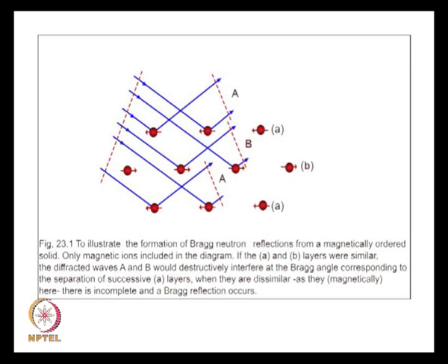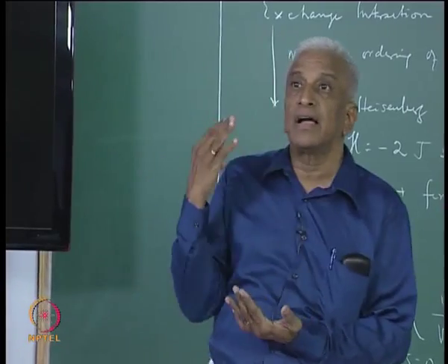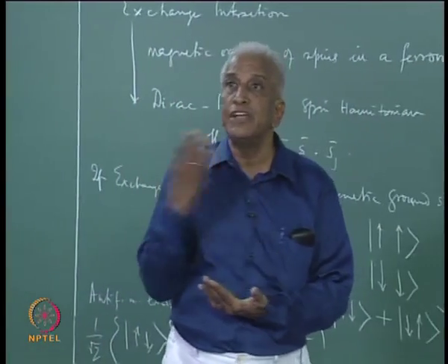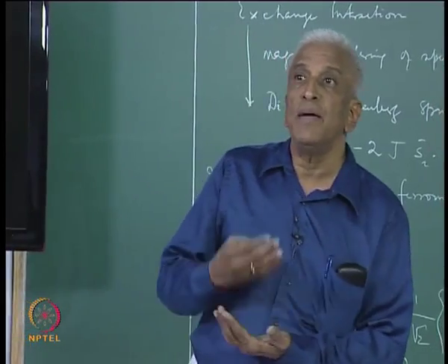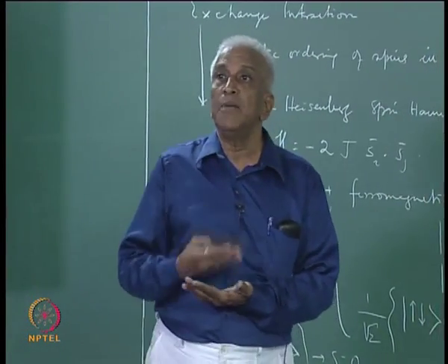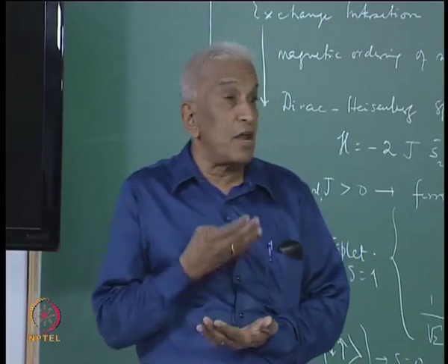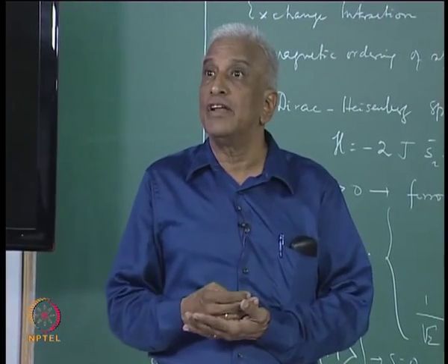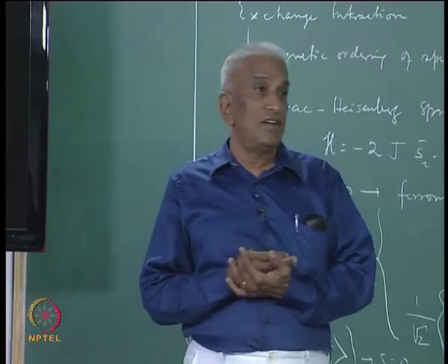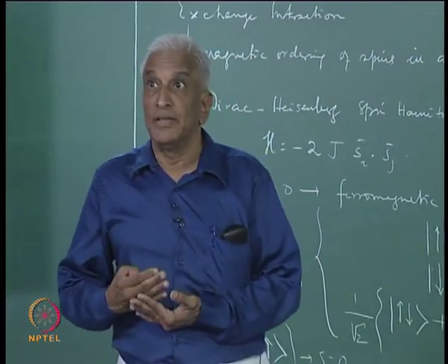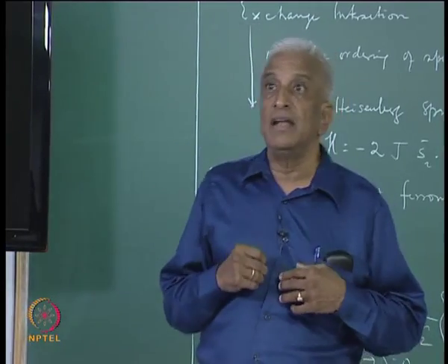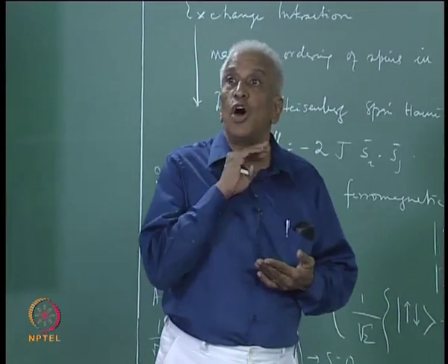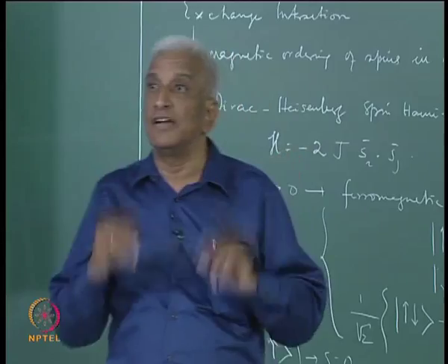different layers in this figure, the A plane ions, and they cause constructive interference and they interfere with the wave fronts from the neighboring B planes with the neighboring A planes, but there would also be destructive interference from the wave fronts from the neighboring B planes, which are through the body center. Because of that, no Bragg reflection would normally occur because of this cancellation.